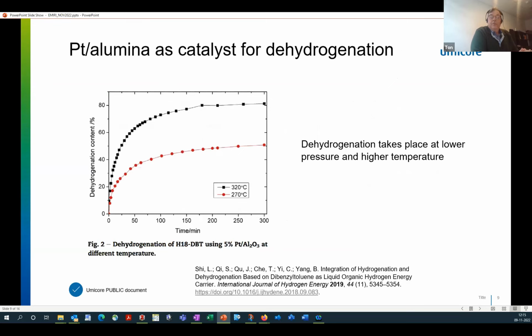Platinum is also good for dehydrogenation. The difference between hydrogenation and dehydrogenation is that the dehydrogenation typically takes place at a slightly higher temperature. So that is around 250 degrees, and you lower the pressure. So hydrogenation is running at 20, 30, 40 bar, and dehydrogenation is essentially running at atmospheric pressure, or maybe up to 5 bar. So that is how you can tune your LOHC process cycle.